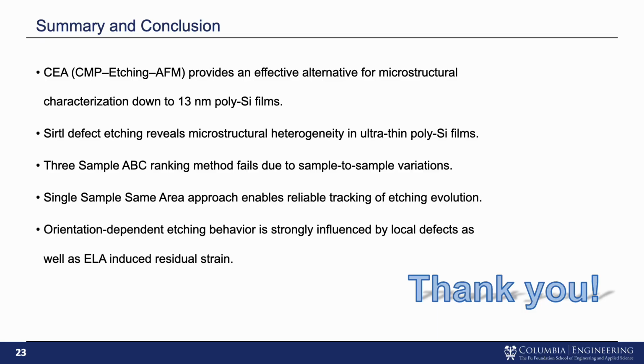From the tracked region analysis, we observed that the orientation-dependent etching behavior is not governed solely by the crystallographic orientations. Local defects and residual strain introduced by ELA play a critical role in modifying the effective etching response. Finally, as discussed in the previous slide, the strong increase in grain plateau roughness and the highly non-uniform response of the brightest regions make it difficult to apply the same etching rate extraction method used previously.